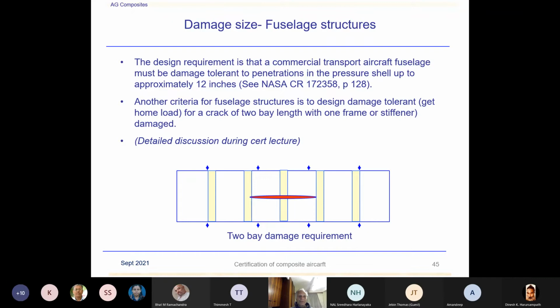So fuselage structure, the design requirement is that a commercial transport aircraft fuselage must be damage tolerant to penetrations in the pressure shell up to approximately 12 inches. And that is what I showed last week when I showed the fuselage requirement. That means the residual strength should be at least the limit load carrying capability. Then there is another subsidiary requirement that when the damage starts propagating, it should be stopped within 2 frames.